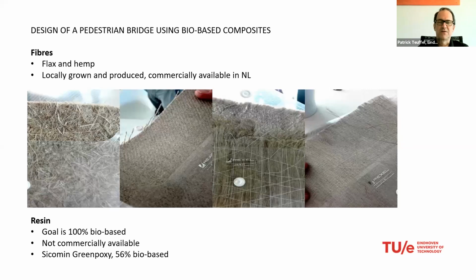Then we looked into different kind of resins. So the goal was to use a resin which is 100% bio-based. But unfortunately, at that time and still until now, these materials are not commercially available. So we used Sicomin Greenpoxy, which is a 56% bio-based resin, which we used in that project.